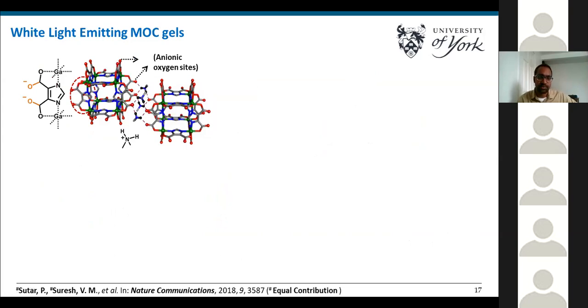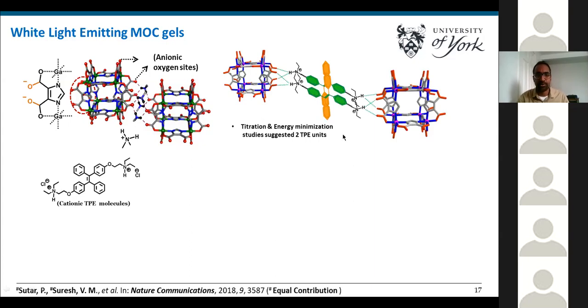For this, you need fluorescent binders. Since the MOCs are able to form hydrogels with any type of hydrogen-donating, hydrogen-bonding molecular binders, we designed this particular molecular binder, specifically to create fluorescent gels. The tetraphenylethene core is highly fluorescent because of its aggregation-induced emission features, and it is functionalized with terminal ammonium cationic groups. This helps in binding the metal organic cages through hydrogen bonding.